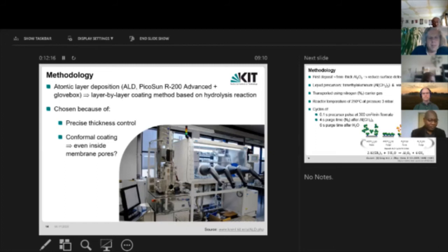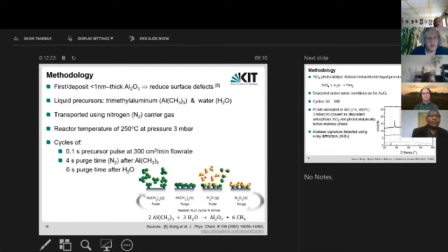So the first step now, preparing our membrane. The membranes are commercial, off the shelf. We're just making them photocatalytically active. But the first step was to deposit a thin, that means less than 1 nanometer thick, aluminum oxide layer. This is just a recipe taken from the literature because it is known to reduce the amount of surface defects present in these membranes after the manufacturing process. It was a bit like a barrier layer, I would say. For this, we use trimethyl aluminium as one precursor. That's our aluminium-containing precursor. And of course, for a hydrolysis reaction, the other reactant that we need is water. These are transported through using a nitrogen carrier gas at 250 degrees C, and the pressure is 3 millibar.